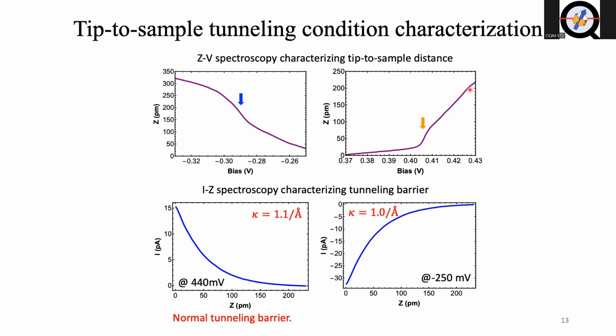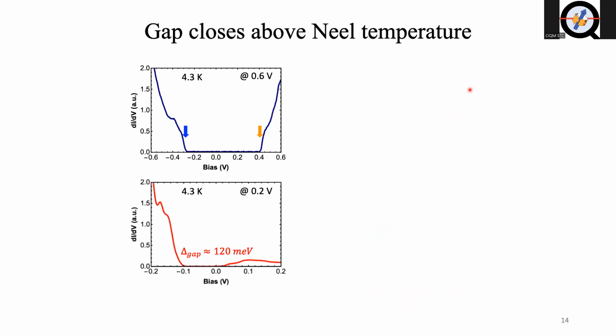And also we did the I-Z spectroscopy to characterize the tunneling barrier to make sure that below and above the threshold energy, we are at a normal tunneling barrier. The tip does not crash. It's still at tunneling regime. So we did the I-Z spectroscopy at constant current at some specific tunneling bias, and I can see that the tunneling barrier, or decay constant kappa, is still within the normal regime, meaning there's still a vacuum tunneling barrier. Yeah, this is to carefully check our spectroscopy. That is correct.